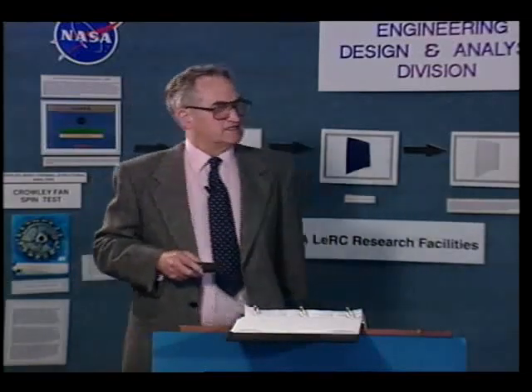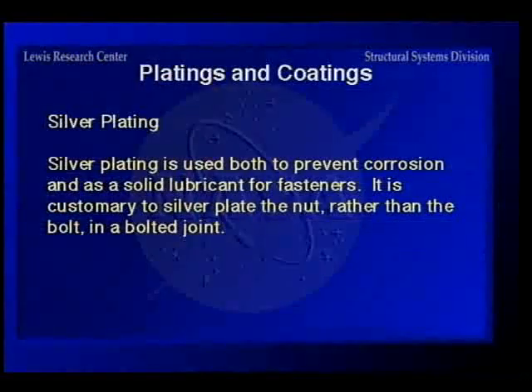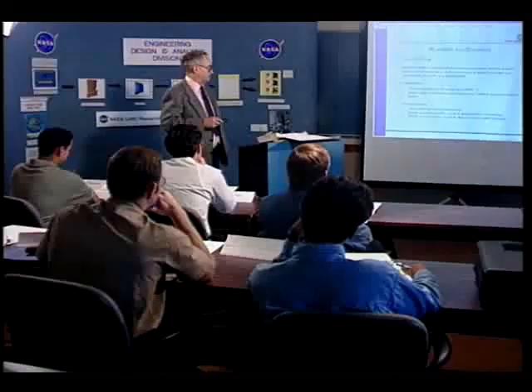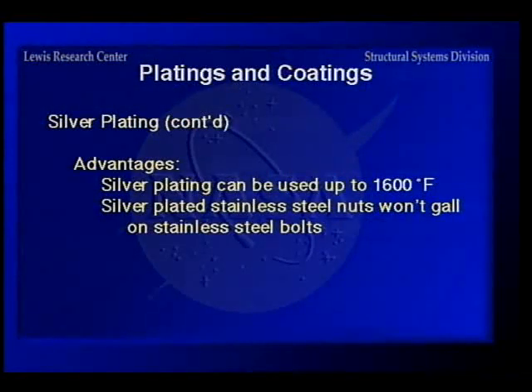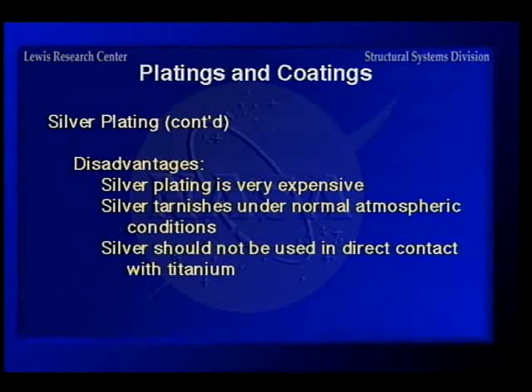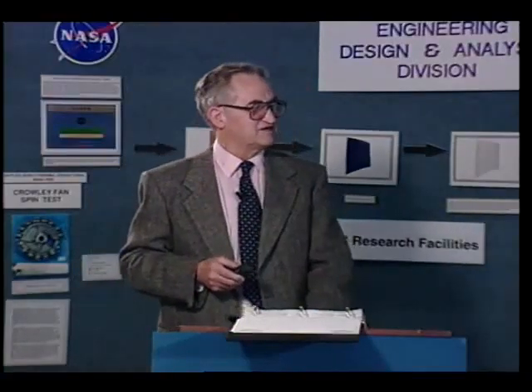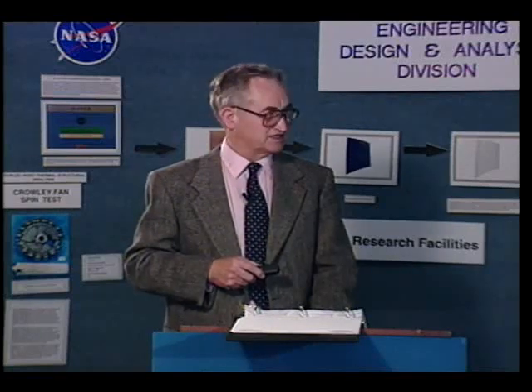Okay, silver plating. Silver plating is used to prevent corrosion and as a solid lubricant for fasteners. For instance, it's customary to silver plate a stainless steel nut for a stainless steel bolt in order to prevent galling and serve as a lubricant. Now, silver plating can be used up to about 1,600 degrees, and its disadvantages, though, it's expensive, it tarnishes, and it shouldn't be used in direct contact with titanium.